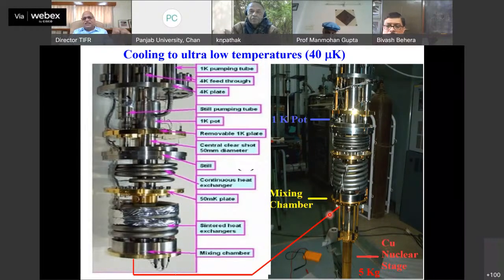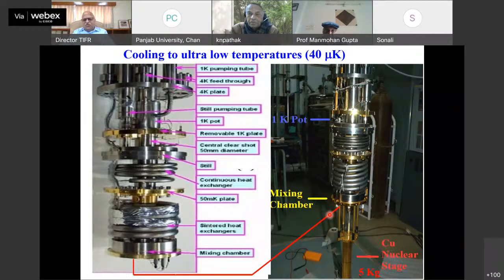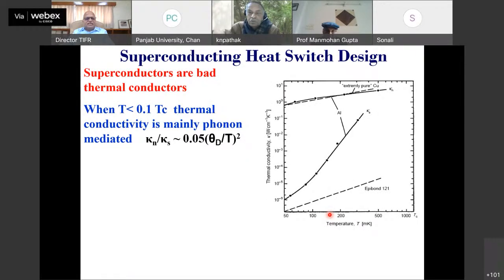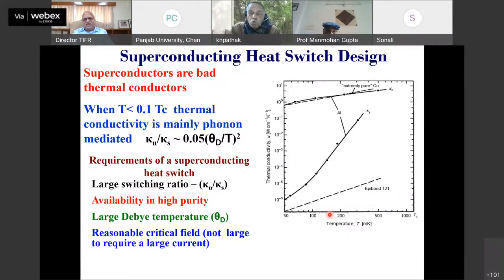What I am telling you is that this kind of refrigeration which we provide can investigate any material. So the point here is that we use this dilution fridge. We cool this 5 kilograms of copper down to about 40 microkelvin. I will tell you that. So as I mentioned, there is a superconducting switch, which is made of aluminium.